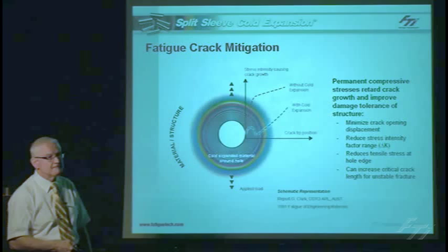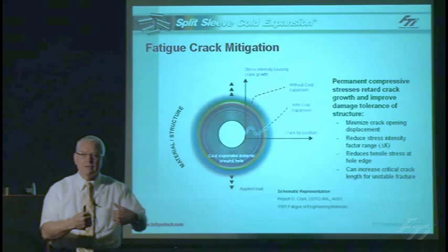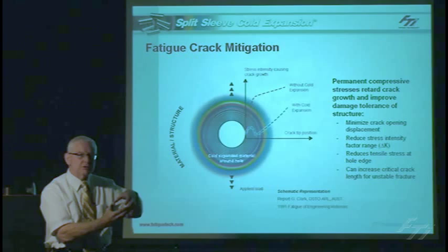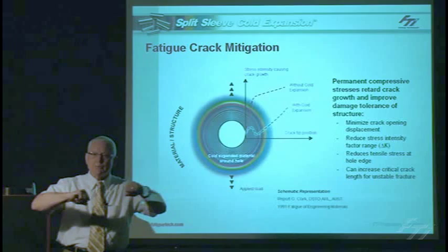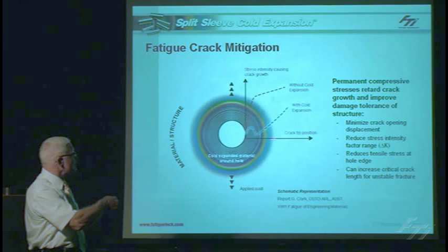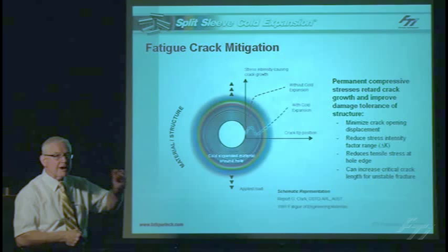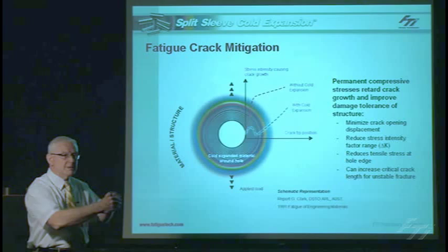A lot of people think that when you go through that residual compressive stress zone, it's just acting like a big spring keeping everything compressed, and as you cut through it the whole thing would collapse. That doesn't occur because you've actually physically yielded that material — it's like that spring I showed you. We have a permanent set and permanently enlarged hole. So even though the crack may continue to grow beyond that residual compressive stress zone, the clamping effect still keeps the crack closed. In fact, we can increase the critical crack length considerably because of that crack closure effect.